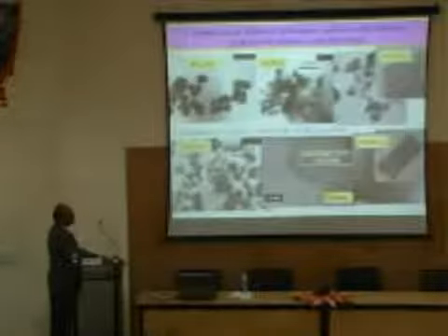We have done a lot of work on making nanostructured dielectric oxides using microemulsions, which are also called reverse micelles. We use a solution of barium, titanium. We have developed some procedures by which we can get these nanoparticles. Earlier I showed you 2 microemulsions, now you need to have 3 microemulsions because you have barium, titanium and oxygen. So there is a protocol to be developed for how you get these particles, and then you look at the TEM, etc. You prove they are nanoparticles, and like that we make a host of others.